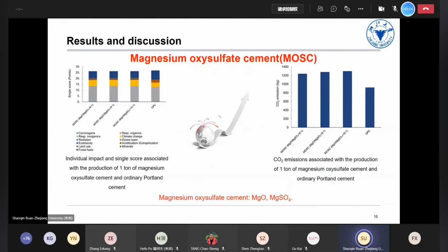That is magnesium oxysulfate cement. Magnesium oxysulfate cement consists of MgO and magnesium sulfate. I performed several evaluations regarding the overall sustainability of MOSC and OPC. We found that the ratio of MgO to magnesium sulfate is irrelevant to the final environmental impacts, and they're quite similar. The overall sustainability of MOSC is comparable with that of OPC, which means it is not quite sustainable.